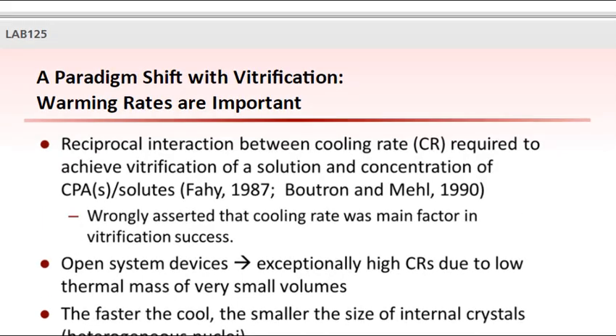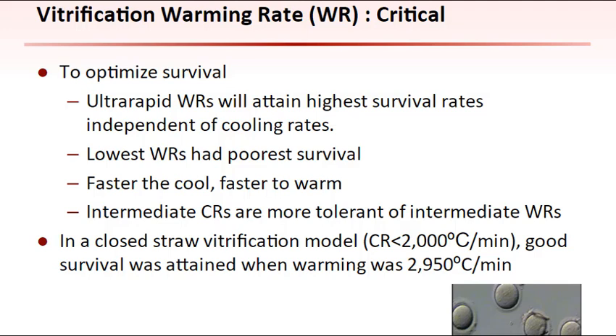A strong reciprocal interaction exists between the cooling rate required to achieve vitrification of a solution and the concentration of cryoprotectant solutes. It had been initially asserted by some that cooling rates were the main factor in vitrification success. This led to open system devices being created that could achieve exceptionally high cooling rates due to the low thermal mass of their very small volumes. The faster the cool, the smaller the size of the internal crystals; the smaller the crystals, the greater the driving force for them to increase in size due to recrystallization during warming. Thus, one needs to warm more rapidly to combat the injurious effect of recrystallization. This led to subsequent findings that vitrification survival is determined by the warming rate relative to the cooling rate.